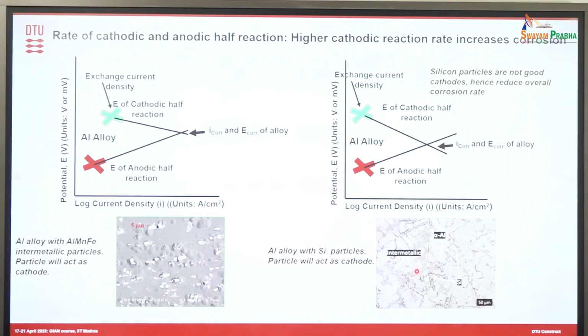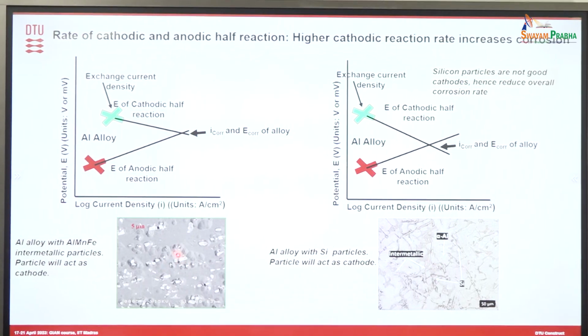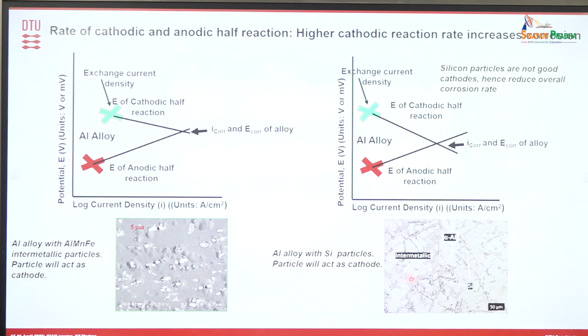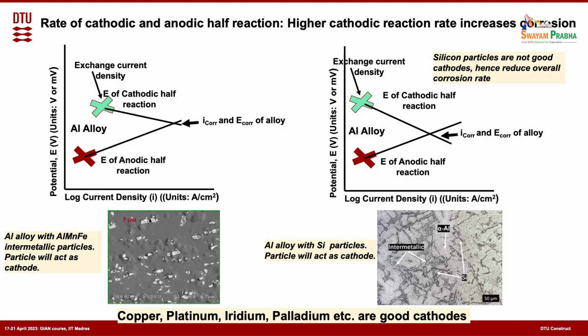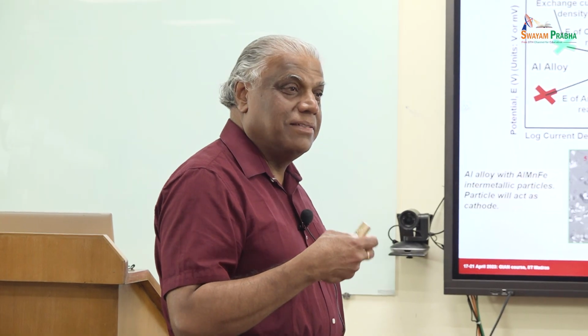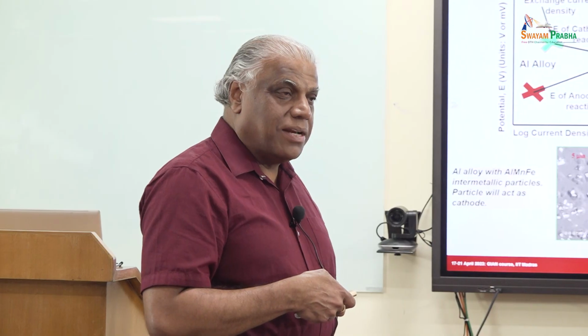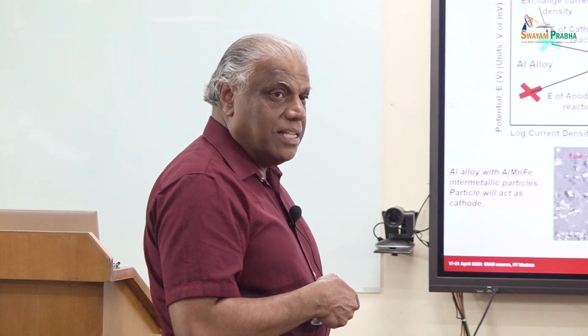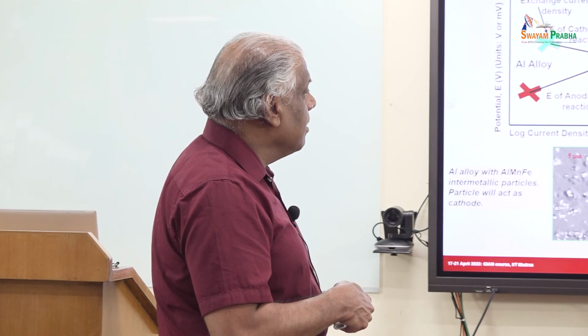If you take these silicon particles, you have a certain area ratio, and if you take the iron particles, a certain area ratio, even if you take the same amount of silicon particles and aluminum iron particles, you will still see that the corrosion rate of this material is higher compared to that of this one. That's because although there is enough area for the silicon and iron here, iron is a better cathode from the point of view of exchange current density. So you can drive more cathode reaction on the iron surface compared to that silicon surface. Silicon is a semiconductor, so it's not a good electrode surface. The reaction occurs very slowly, so the exchange current density is lower, and that way you get a lower corrosion rate here.